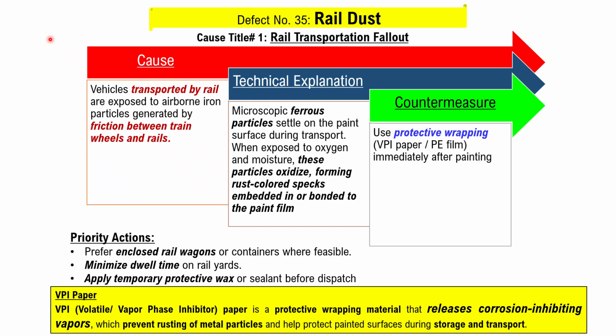Coming to the causes and countermeasures. Number one probable cause would be rail transportation fallout. That is, vehicles transported by rail are exposed to airborne iron particles generated by friction between train wheels and rails. Microscopic ferrous particles settle on the paint surface during transportation when exposed to oxygen and moisture. These particles oxidize, forming rust-colored specks embedded in or bonded to the paint film.